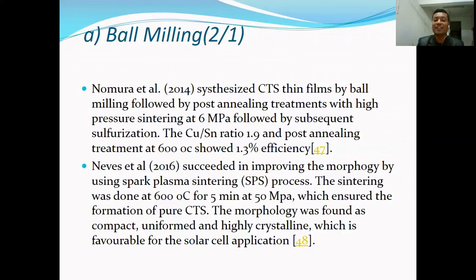In 2016, they succeeded in improving the morphology by using the spark plasma sintering process. The sintering was done at 600 degrees Celsius for 5 minutes at 50 MPa, ensuring the formation of pure CTS. The morphology was found to be compact, uniform, and highly crystalline, which is favorable for solar cell application.